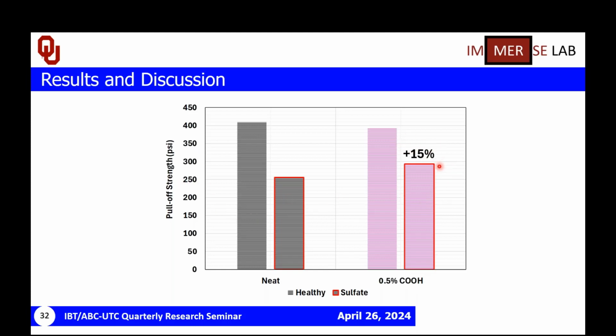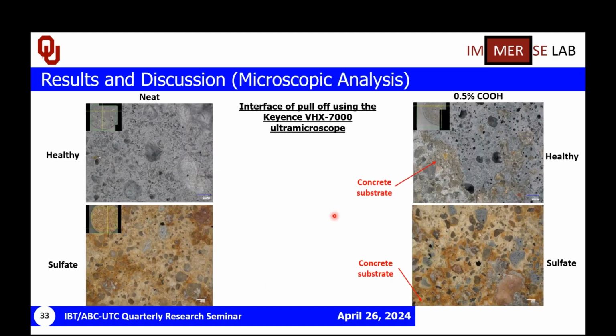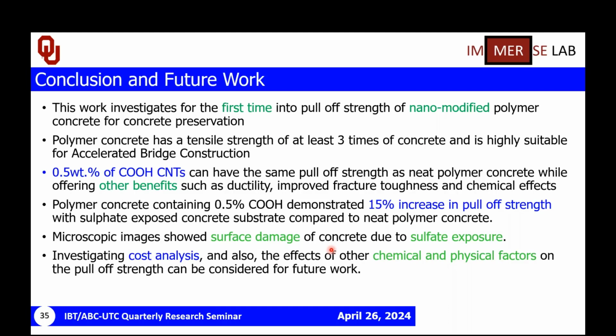Now I will conclude our presentation by providing some of the conclusions. This work investigates for the first time the pull-off strength of nano-modified polymer concrete. As you can see from the obtained results, the polymer concrete has a tensile strength at least three times that of the concrete. The 0.5% COOH functionalized type of carbon nanotube showed similar pull-off strengths as neat polymer concrete in the healthy situation, while offering other benefits such as ductility, improved fracture toughness, and chemical effects.